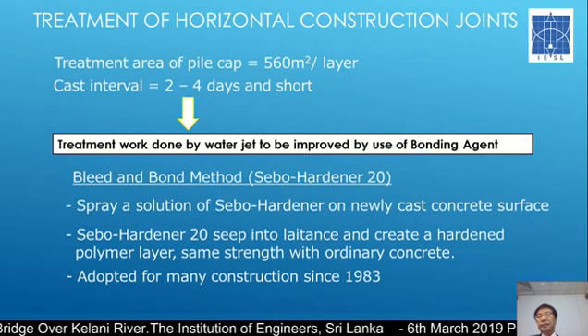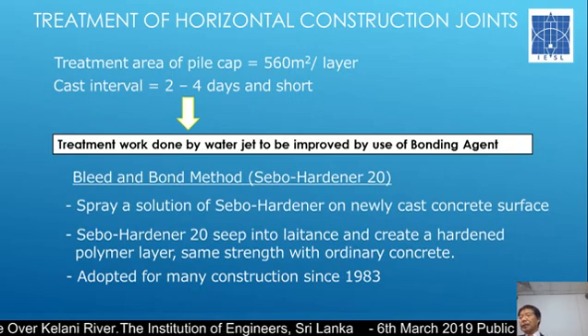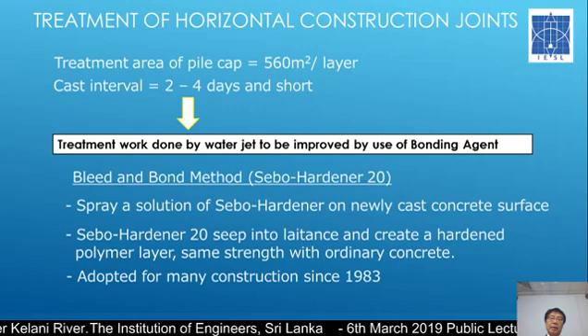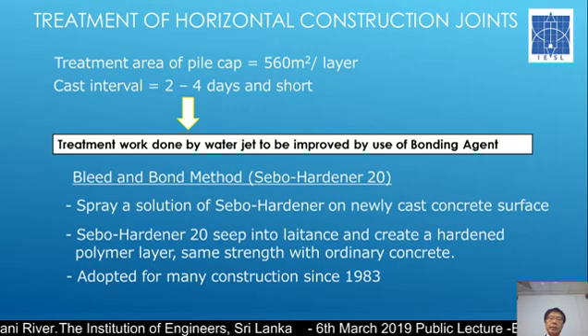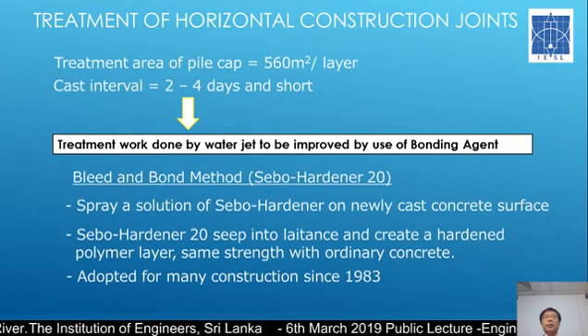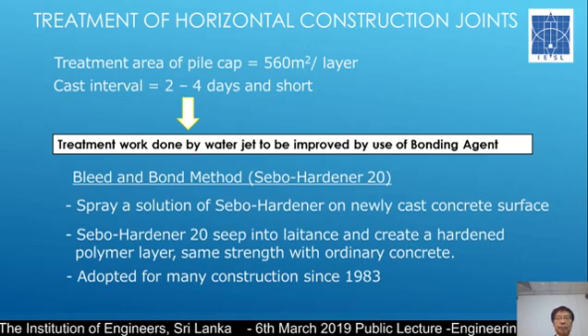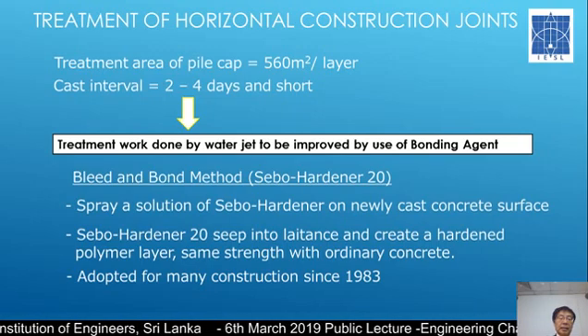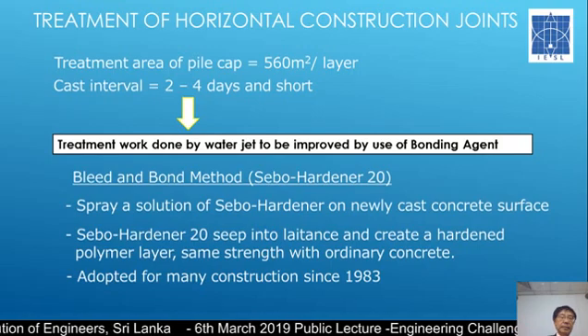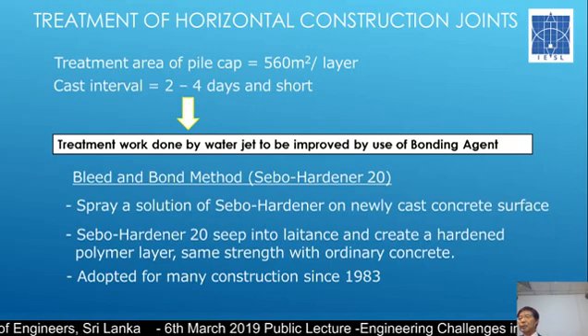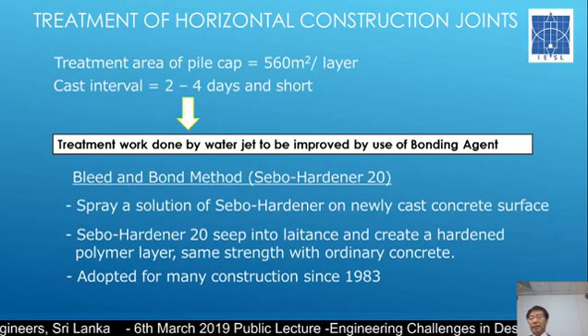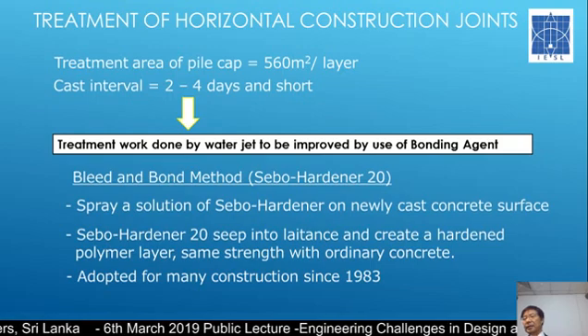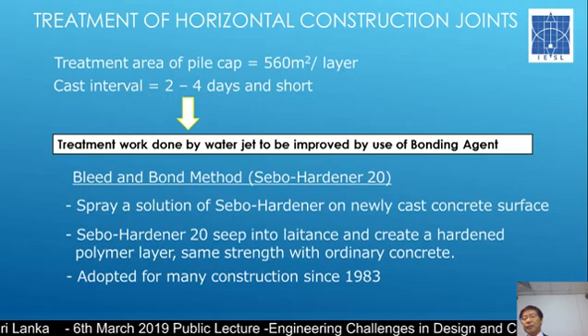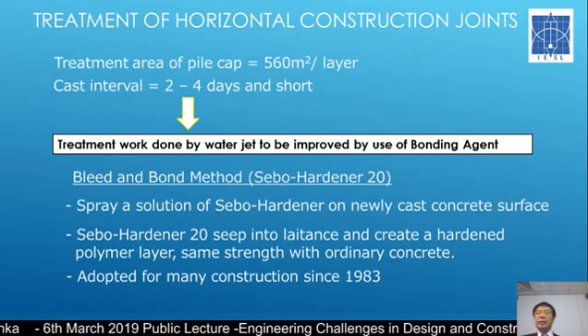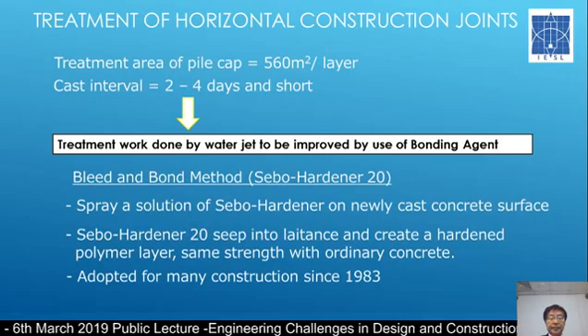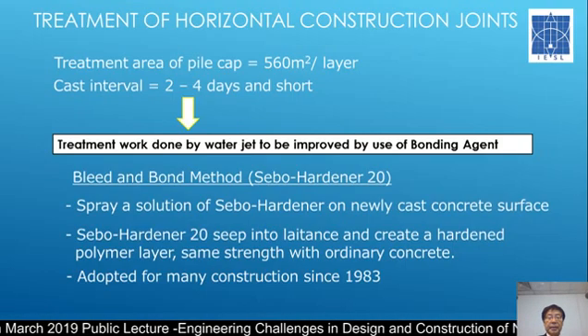For the 5 layer case, because of the multiple layers, you have to do some green cutting, and usually that is done by high pressure water jet, but it is very costly. It takes time, and the treatment of the water is not easy. So the contractor proposed the use of some bonding agent between the concrete layers, which does not remove the laitance, but is an adhesive, a liquid laid over the first layer, that suppresses the bleeding and mixes with it and makes a very hard layer of polymer. So this is used for this project.